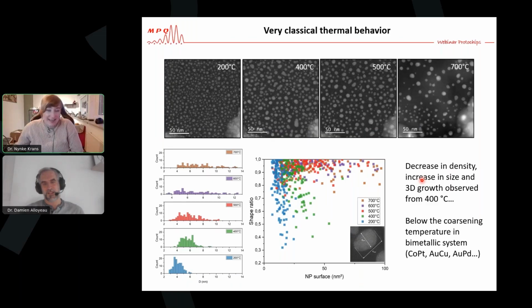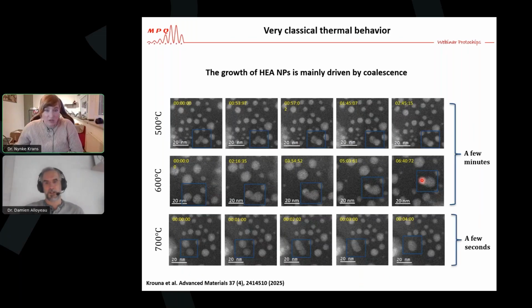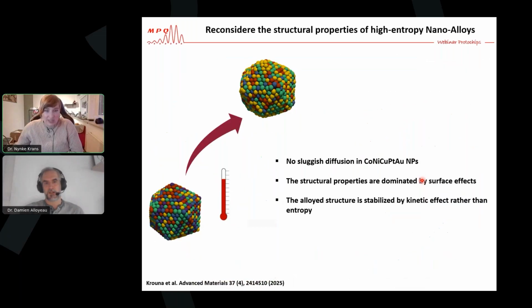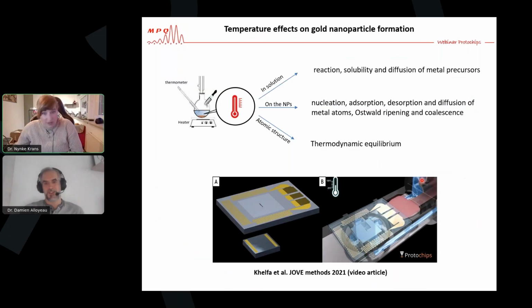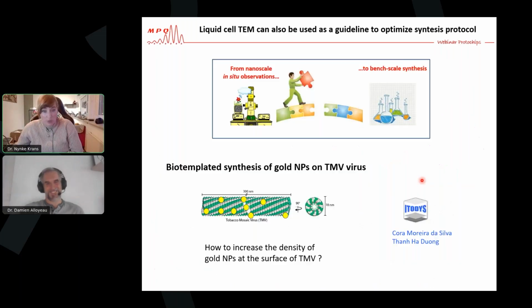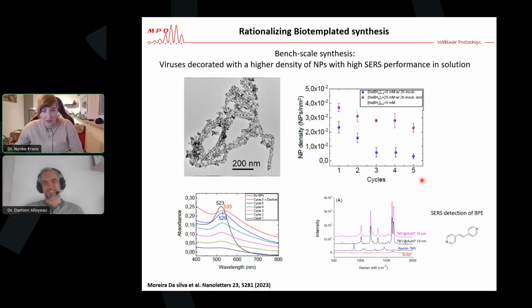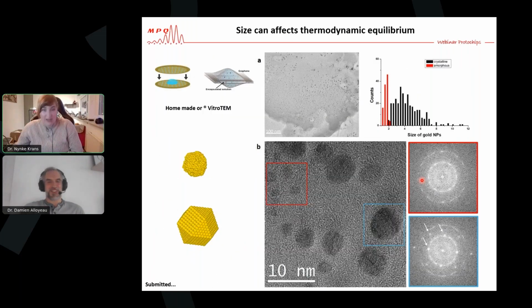A second question is, and I'm assuming this is about the graphene liquid cell work, I'm not 100% sure, but she's saying an amorphous looking FFT does not necessarily mean the particle is amorphous. It could also mean that the crystal is just not oriented close to its own axis, or that the particle is too small or too defective for clear spots to appear. Very interesting question. Thank you for asking that.